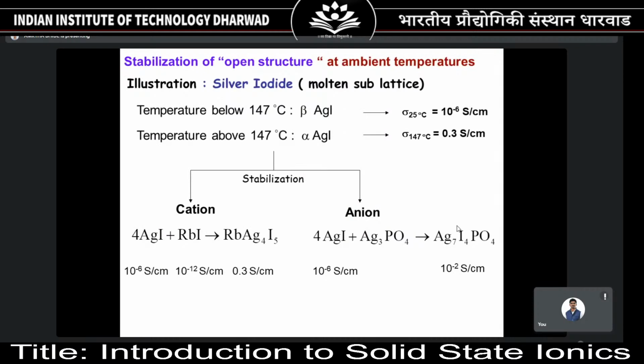So people started working in the late 90s on stabilization of the open structure. Look at this diagram, or look at these values. Beta AgI, below 147 degrees Celsius, has conductivity of the order of 10 to the power minus 6 Siemens per centimeter. After it has undergone a phase transition, there is a 5 orders of magnitude enhancement in the conductivity at 147 degrees Celsius. And there is something called stabilization of the open structure. The structure which enables the ionic conductivity has to be stabilized. What they did is they mixed rubidium iodide with the silver iodide. Here, this is ionic conductivity of 10 to the power minus 6. Rubidium iodide has conductivity of the order of 10 to the power minus 12 Siemens per centimeter. It's typically an insulator, you can say.